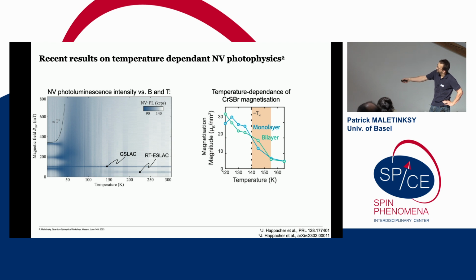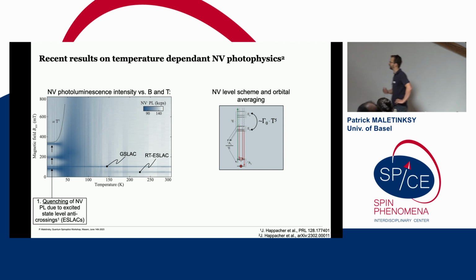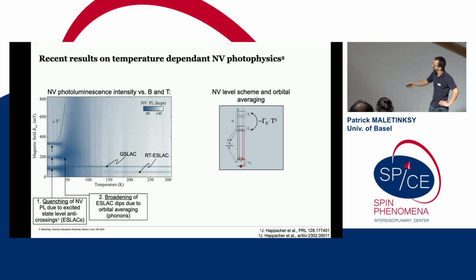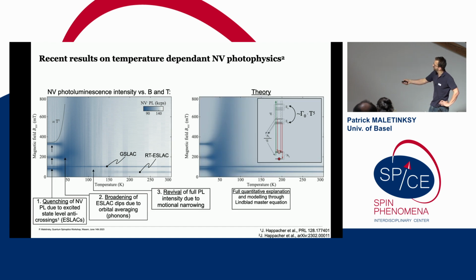This is data that shows you the NV photoluminescence intensity as a function of magnetic field and temperature. And you see this rather peculiar shape here, which, and this is what I want to conclude with, we can by now fully and quantitatively understand using a rate equation model, essentially a Lindblad master equation, that takes into account the level structure of the NV center. I will not go through individual steps here. We can talk about this later on. The takeaway message is we fully understand that this is our theory model that essentially captures what we see experimentally.